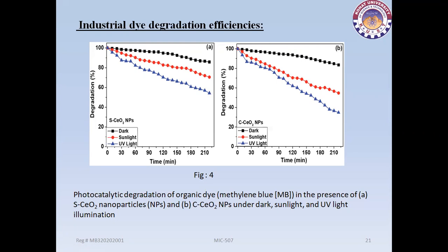And under sunlight and UV light, the catalysts showed better performance than in dark. The degradation efficiency of cubical cerium oxide nanoparticles under sunlight and UV radiation was superior to spherical cerium oxide nanoparticles. Under UV light, cubical cerium oxide nanoparticles exhibited efficiency around 70%, whereas spherical cerium oxide nanoparticles only expressed efficiency of less than 50% over the course of the measurement time.